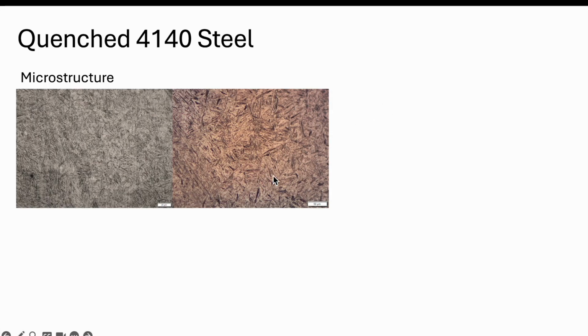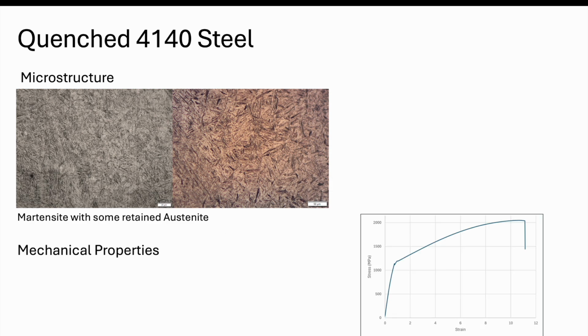Like I said, it's predominantly martensite, all these tiny little lenses that we see in these structures, these little thin needles. And some of the lighter regions can be austenite that hasn't transformed, or retained austenite. So that's what we expect with this microstructure. We're going to see martensite with some retained austenite. So let's look at what that results in on the mechanical properties side.